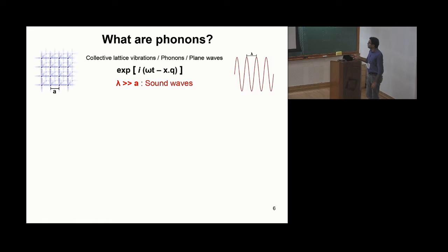These phonons are precisely the ones which carry sound energy through crystals if their wavelength lambda is much longer than the spacing between the atoms. But what I am really interested in are those phonons with wavelength comparable to the lattice spacing. When lambda is very small, those are the phonon modes which carry heat through semiconductors.